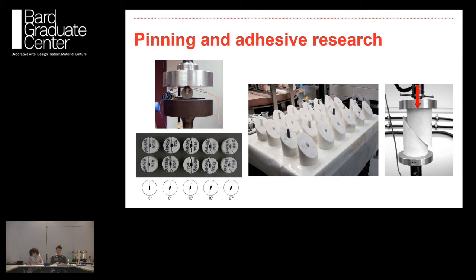Much of what we had to draw on in terms of past research on large-scale sculpture was based on the treatment of ancient sculpture, which often has large gaps between the joins due to degradation of fracture surfaces over time in burial, as well as from campaigns from previous restorations. Because the joins in Adam's legs were very tight, and because there was an uneven number of breaks in the left and right legs, the thinness of the joints had a direct effect on the success of the treatment.